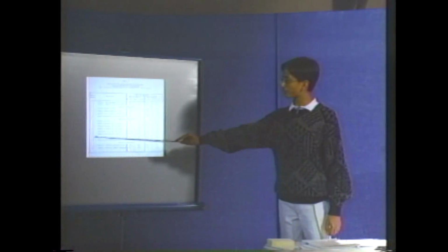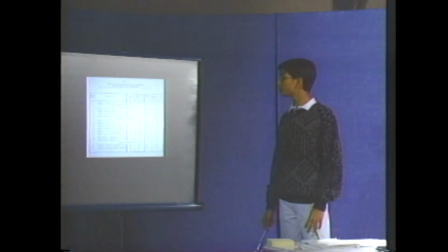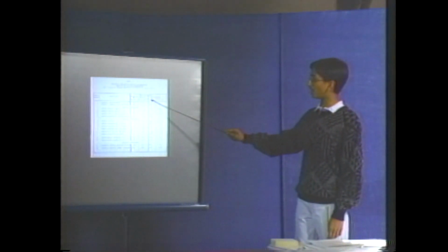A select group of non-ionic surfactants, samples number 13 and 14, also showed excellent static elimination. Only one anionic surfactant, sample number 4, showed decent static elimination. It may also be noted that heat treatment did not alter performance. It may further be noted that after the samples were washed, regardless of whether they were heat treated or not, all samples lost static protection.